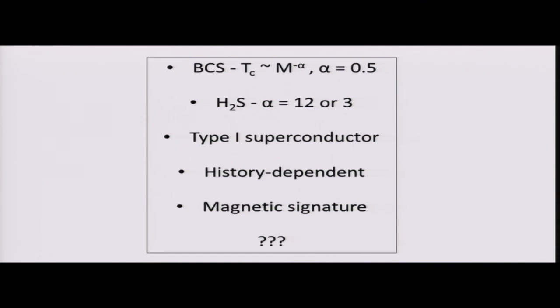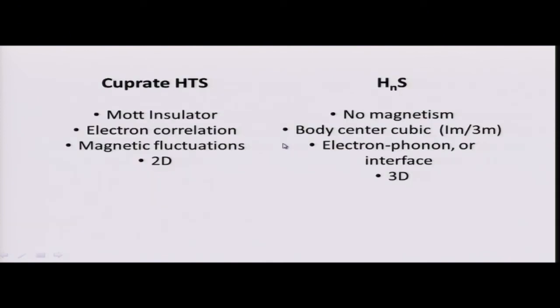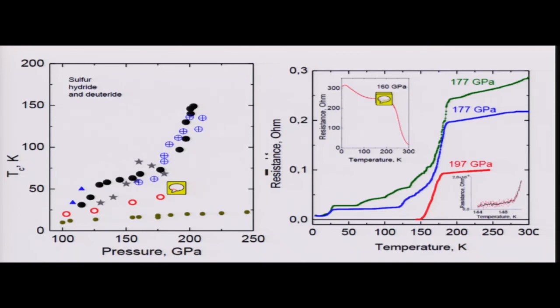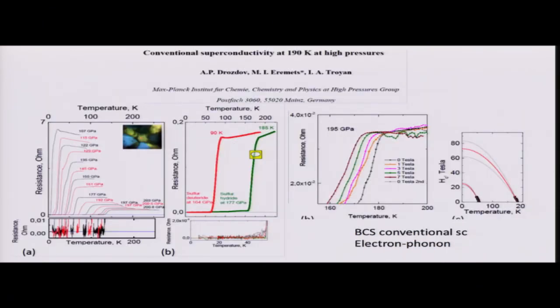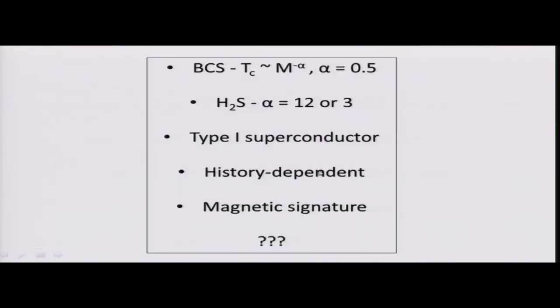So all this, they concluded it must be a superconducting transition. But the interesting thing is that according to BCS theory, the Tc is proportional to the isotopic mass to the minus alpha. Alpha should be 0.5. In this case, it's around 12 or 3, depending on which transition you're looking at. It also looks like a type 1 superconductor because all those curves are suppressed in parallel with field. Usually at high Tc, you have flux pinning, and it should be broadened instead of in parallel. So this is another question we don't understand in this case.